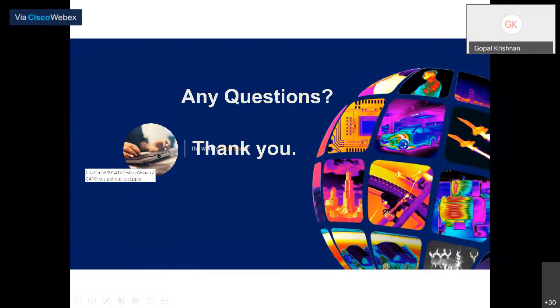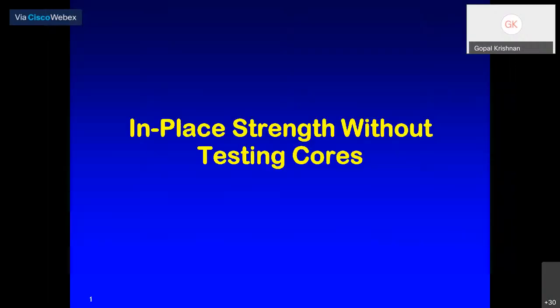Thank you for that, and we'll move on with another interesting one. Nowadays, if you want to know the strength, everybody definitely goes for taking the core and getting the strength tested by the laboratory. This process takes 4 to 5 days. In this, taking the proper coring, trimming it to parallel, and curing it 48 hours before testing with a capping. Then applying the load systematically. That is also very important. Otherwise, the majority of the cores fail.